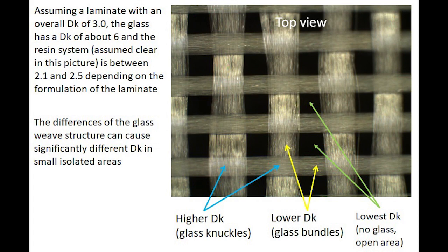And then finally, the green arrows are pointing to areas where there is no glass. That's an open area of the weave. And in that area, it would just be resin only. And typically, the resin is going to be much lower in dielectric constant.